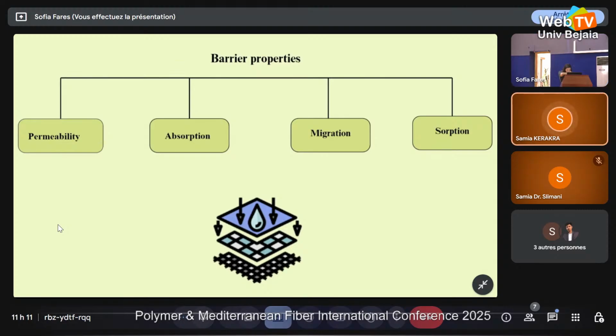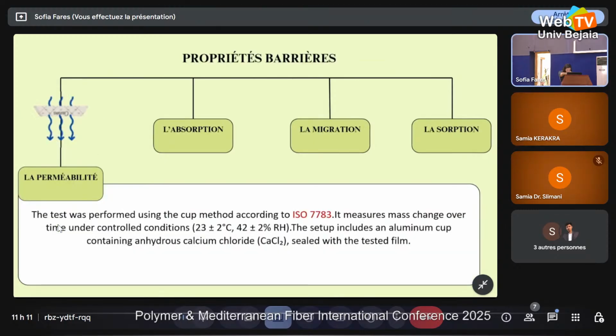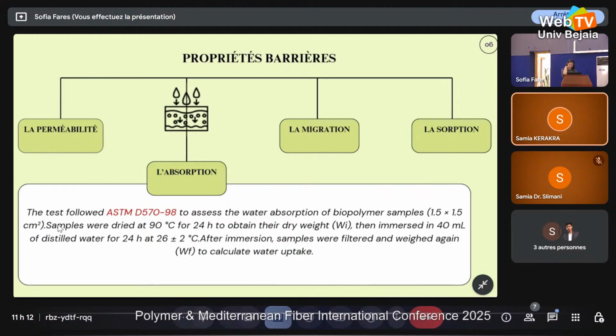Let's begin with the permeability, please. Our test was performed using the cup method according to ISO 7783, which measures mass change over time under controlled conditions like temperature and humidity, and this test is well known. The second one, absorption. The test followed ASTM D570 to assess the water absorption of polymer samples, and this one also is very well known.